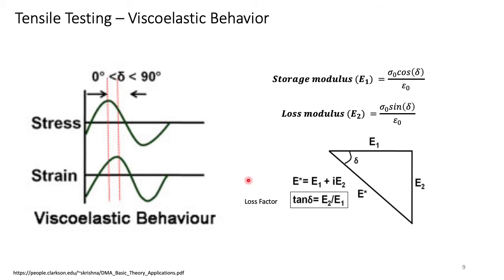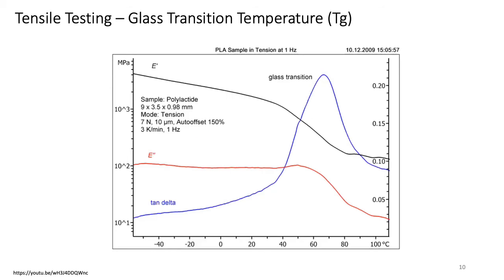And then we can also find the loss factor, which is the tangent of the phase angle. The reason why storage modulus, loss modulus, and loss factor are important is that they can help us determine the glass transition temperature of the material. So let's take polylactide as an example. As you can see here, they plot the storage modulus, loss modulus, and also the tangent of the phase angle, and then they determine the glass transition temperature at the glass transition region, which happens at around 70 degrees Celsius. And that's the glass transition temperature of the material.